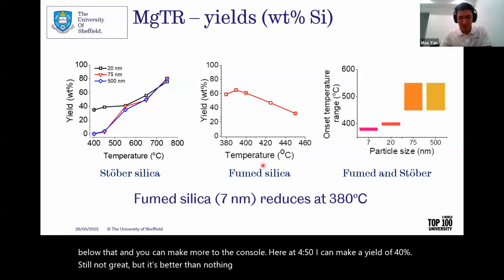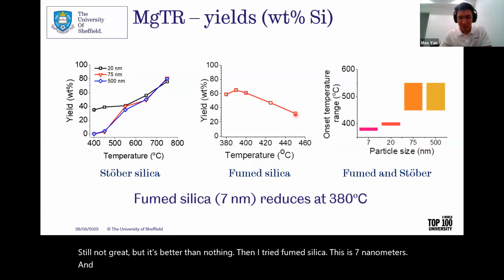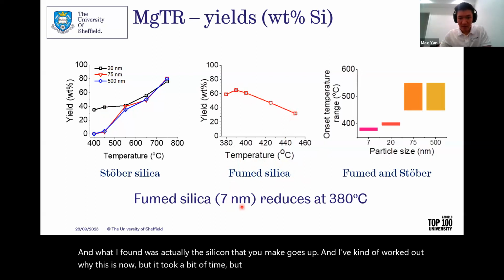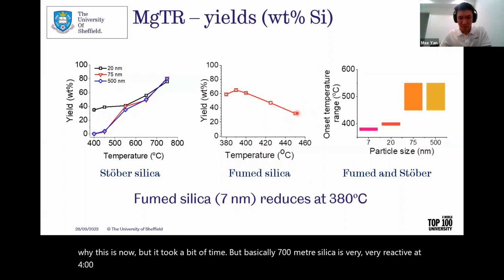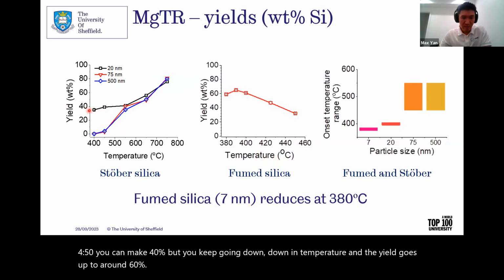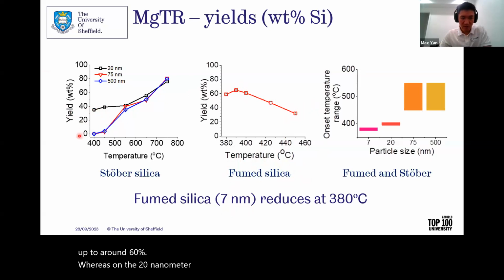Then I tried fumed silica. This is 7 nanometer silica. And what I found was actually the silicon that you make goes up. I've kind of worked out why this is now, but it took a bit of time. Basically, 7 nanometer silica is very, very reactive. At 450, you can make 40%, but you keep going down in temperature and the yield goes up around 60%. Whereas on the 20 nanometer silica, it actually just goes down to zero. Nothing happens anymore below 400.